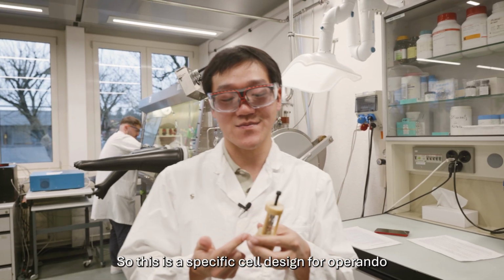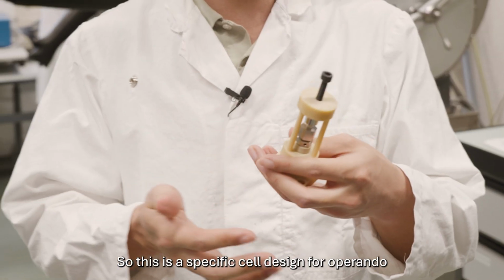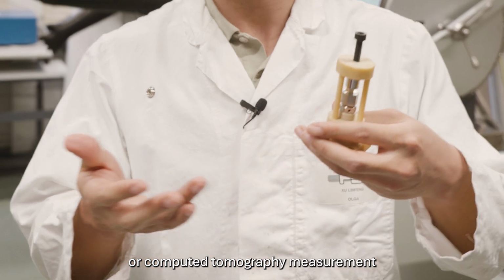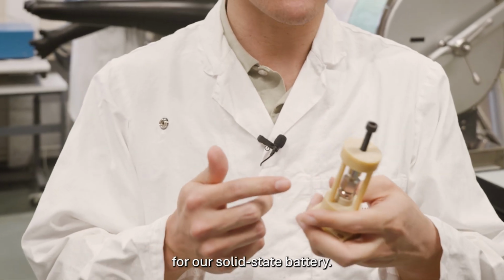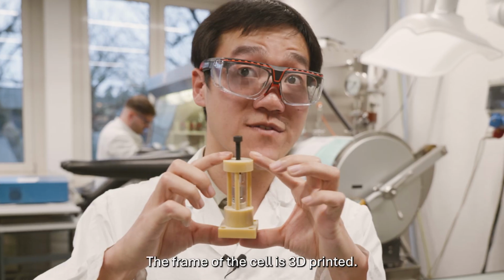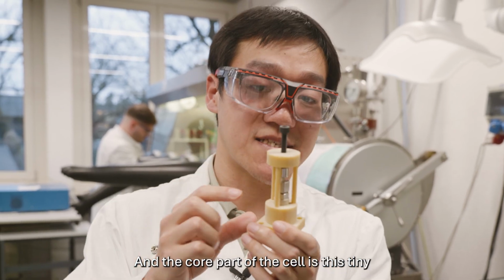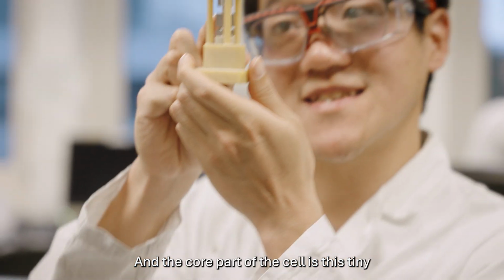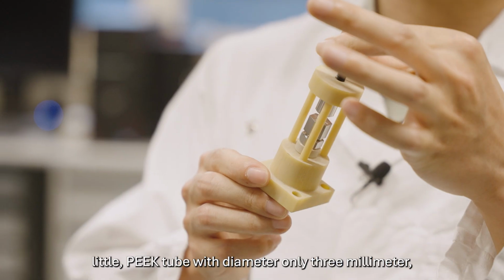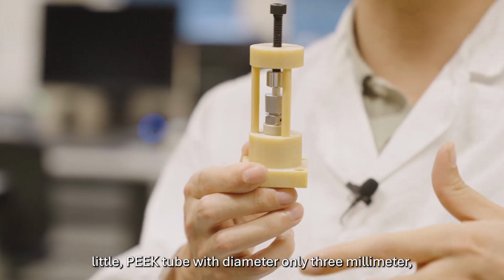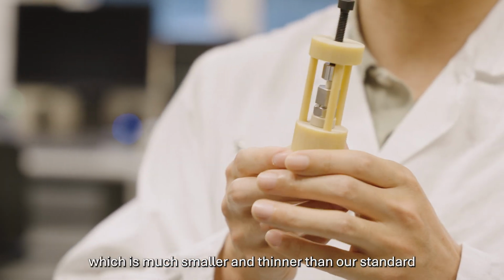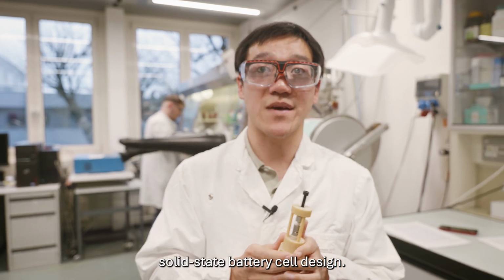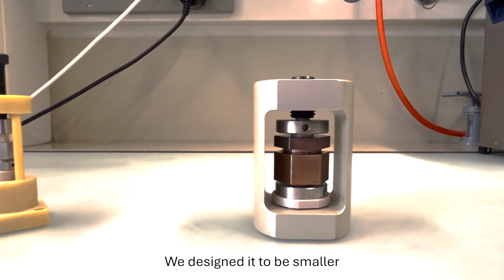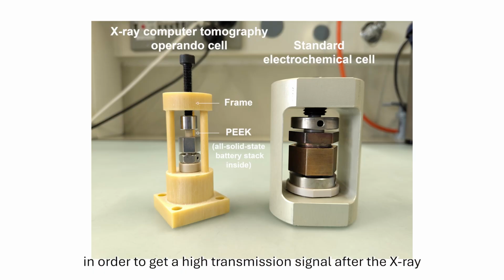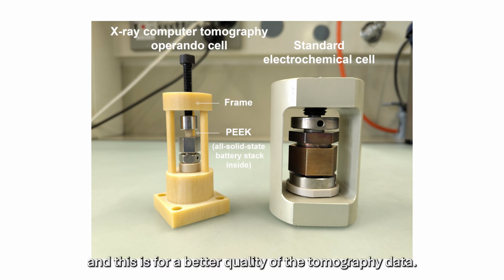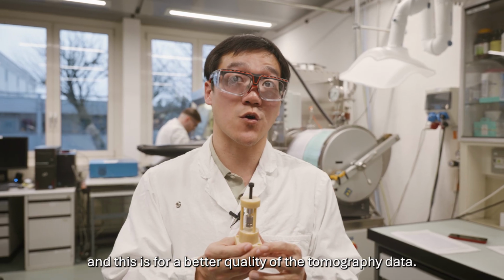So this is a specific cell design for operando XCT, or computed tomography, measurement for our solid-state battery. The frame of the cell is 3D printed, and the core part of the cell is this tiny little PEEK tube with a diameter of only 3 mm, which is much smaller and thinner than our standard solid-state battery cell design. We designed it to be smaller in order to get a high transmission signal after the X-ray, and this is for better quality of the tomography data.